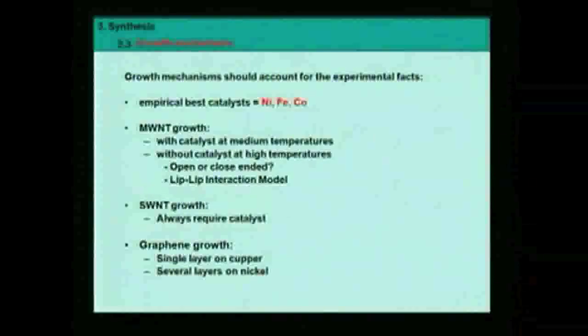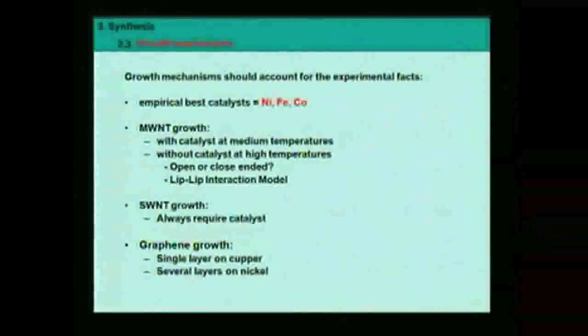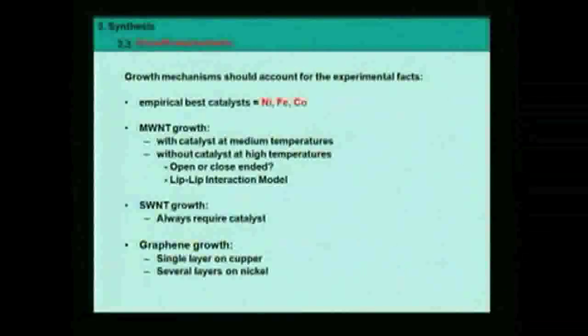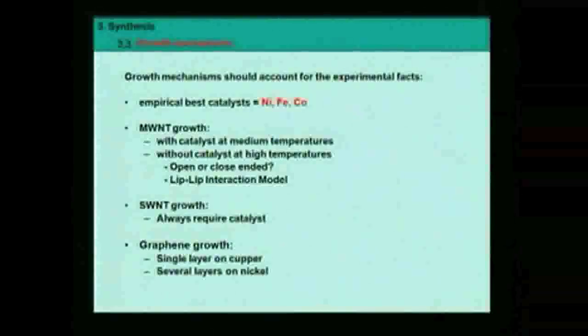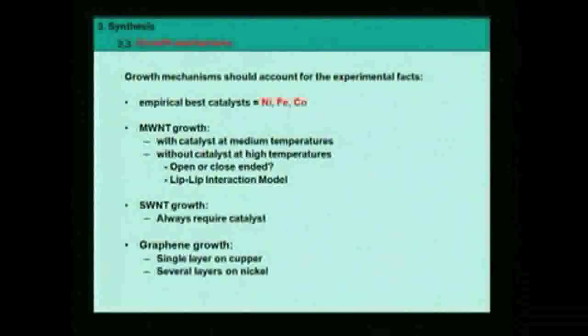As I said, the growth mechanism, if we want to propose something realistic, has to account for experimental observations. So we can cite some important experimental observations. First, the best catalysts are nickel, iron, and cobalt. We already provided some good explanations for why those catalysts are the best for nanotube and graphene growth, thanks to their intermediate carbon affinity.